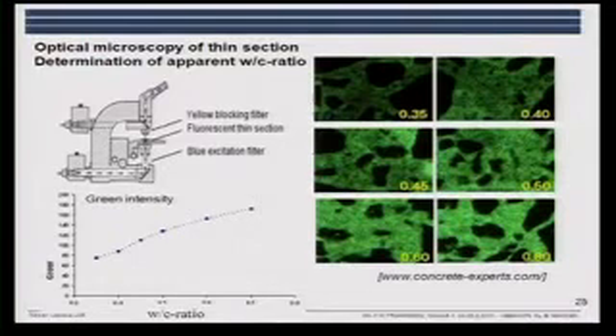And I told you earlier that the thin section technique could be used for estimating the capillary porosity. And here you see some reference samples which have been prepared by a Danish company. And you can see the relationship between the green intensity and the water cement ratio, 0.3, 0.4, 0.5, 0.6. And it's a fairly good technique. If you're trained comparing samples, and if the samples are homogeneous, you can do it with an accuracy of 0.2 or so.